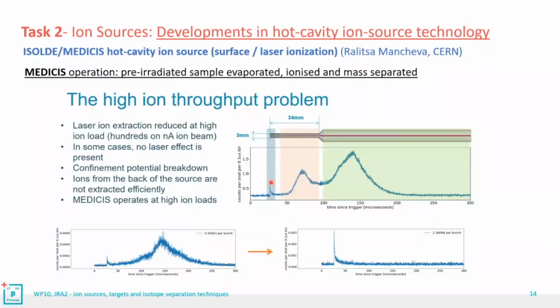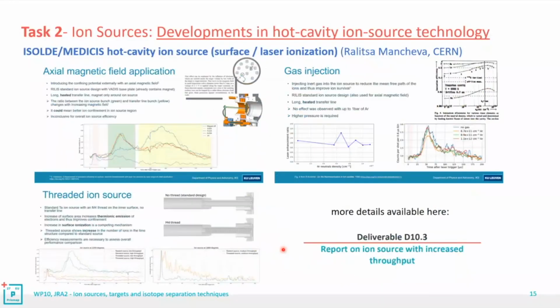You can see the effect in normal conditions. Here you can see the laser extracted ions at the extraction region, in the region of the hot cavity, in the region of the transfer line. When you increase the ion load, this curve becomes flat, as you can see in this graph. To address this problem, colleagues from CERN defined 3 different experimental tests. In the first one, they imposed an axial magnetic field in proximity of the hot cavity. In the second one, they injected inert gas, argon, into the ion source to reduce the mean free path of the ions, so as to improve ion survival.